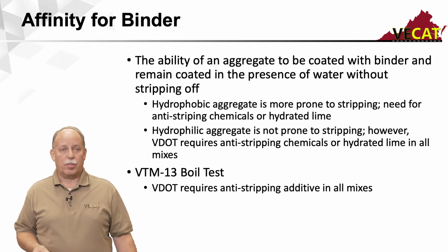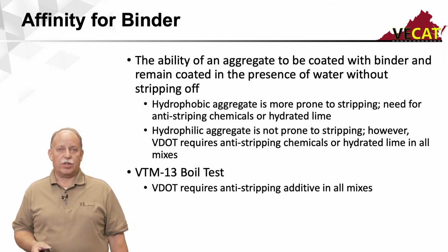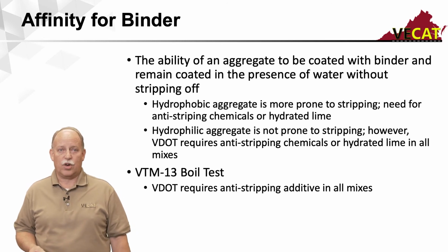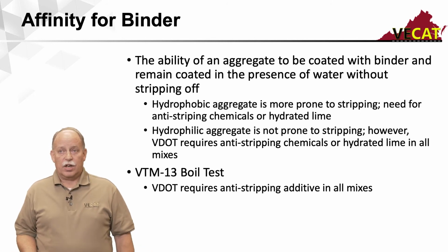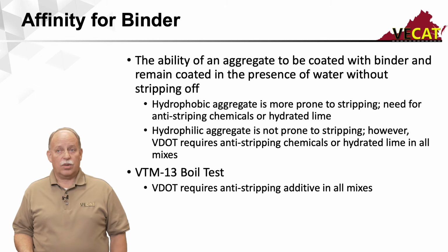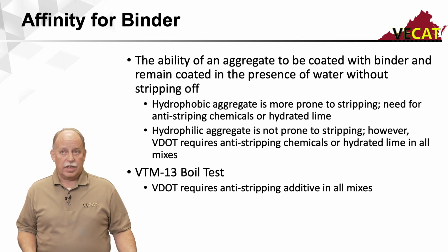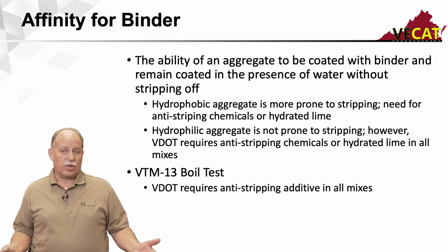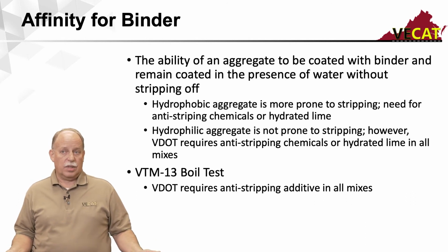The affinity for the binder. This is the ability of the aggregate to be coated with binder and remain coated in the presence of water without stripping off. Our aggregates are either hydrophobic or hydrophilic. A hydrophobic aggregate is more prone to stripping, and the need for anti-stripping chemicals or hydrated lime is obviously present. A hydrophilic aggregate is not prone to stripping.